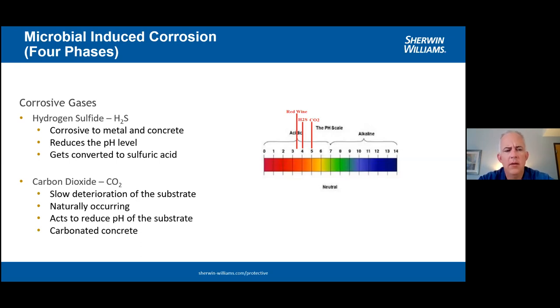We also have the presence of carbon dioxide, CO2, in our collection system and in our wastewater treatment system. CO2 gas slowly deteriorates the concrete. It's not quite as aggressive as what we have with the hydrogen sulfide gas. It's something naturally occurring, and it also acts to reduce the pH of the concrete, but not quite as aggressive as what hydrogen sulfide does. And a result of this is carbonated concrete, which is a soft, powdery, kind of a mushy concrete, if you will.